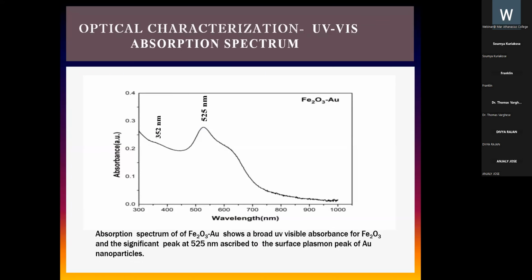This is the UV visible absorption spectrum of the nanocomposite. Iron oxide exhibits a broad UV visible absorption. The peak at 352 nanometer results from the ligand to metal charge transfer transition of iron oxide. And a significant peak at 525 nanometer can be attributed to the plasmonic peak of gold nanoparticles.